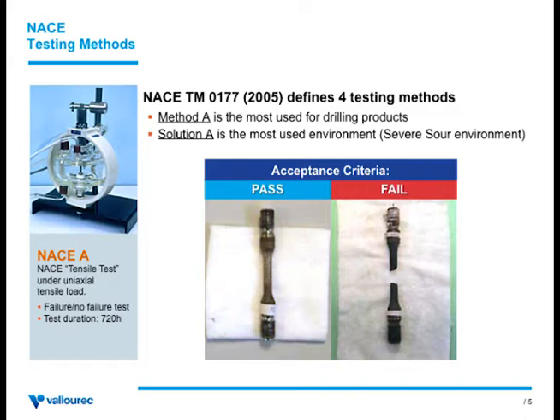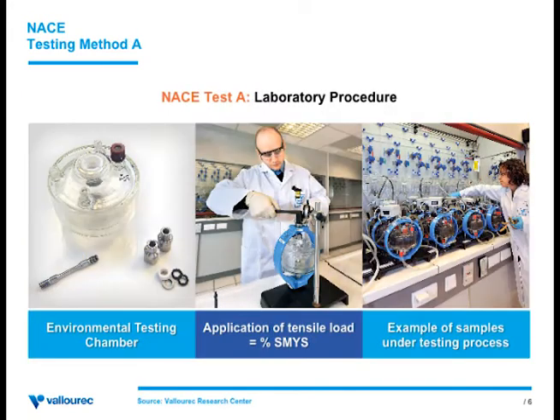And the test is not quantitative. It's not going to tell you, well, you can use this pipe for 5,000 rotating hours in a sour well. It's a go, no-go test. If the sample passed the test, then we consider that the drill pipe is okay to be used. If the sample fails, then there will be corrective actions that would have to be taken. For example, another heat treatment, or eventually completely scrap the batch and remanufacture the drill pipe.